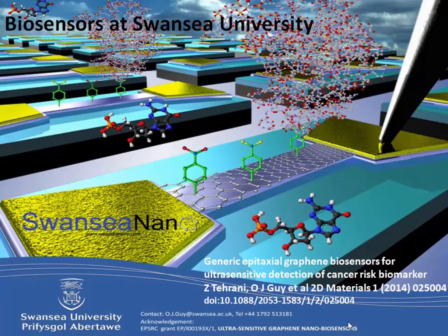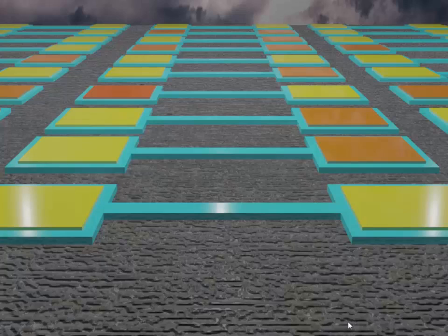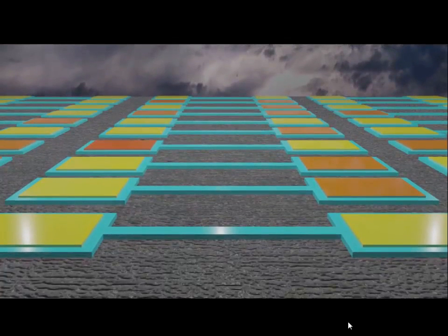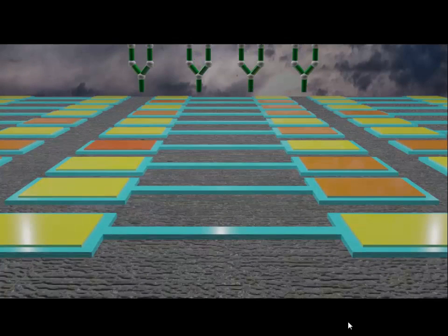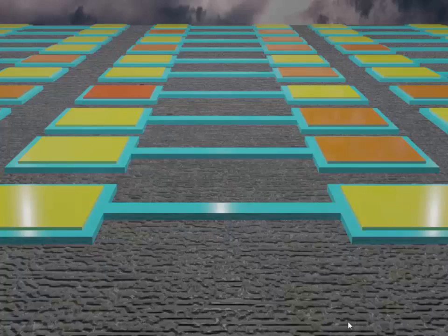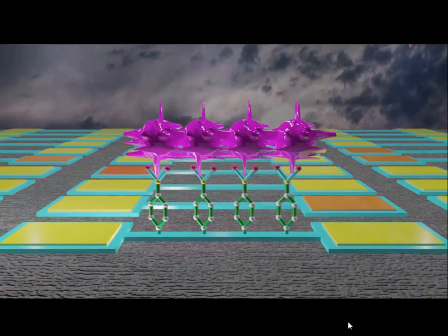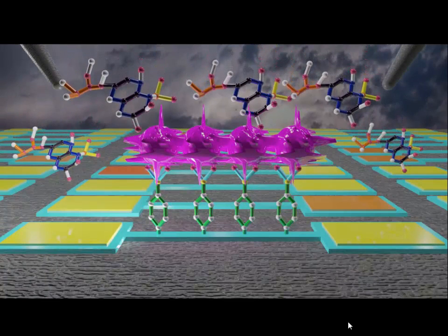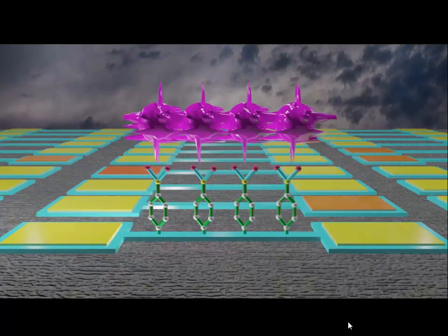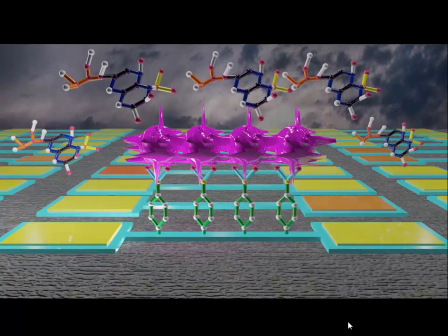Okay, so what we're trying to do then is use these nanofabrication techniques to create sensors. Very simple sensor structure, a channel between two metal electrodes, and then we're going to functionalize this channel. So there's our channel. This can either be silicon or it can be graphene, and we're going to functionalize using a linking molecule. There are several linking chemistries that we use. We use silane, but we also use a diazonium molecule. The crucial part is attaching this amino group to the surface. There's our antibody detecting our biomarker, and it's a very simple current voltage measurement, changing the conductivity of this channel.